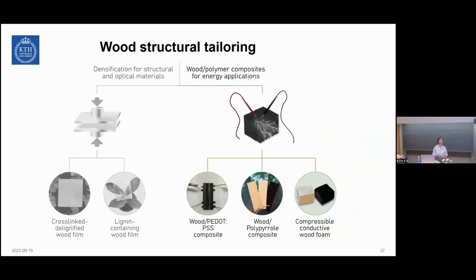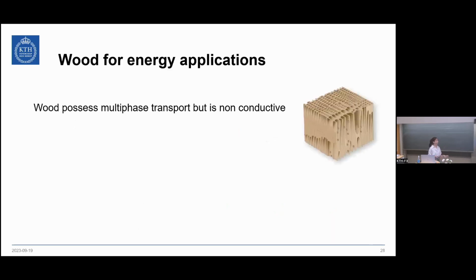So we've seen how to tune wood structure towards densification and optical and structural material. We also try to tune the wood structure so that the interaction with the polymer could be improved for use in energy application. Wood has already been used in energy application, and the reason for this is that it possesses multi-phase transport, which means that there are a lot of low tortuosity channels inside the wood, which are the lumen space. And this can be used for the conduction of ions.